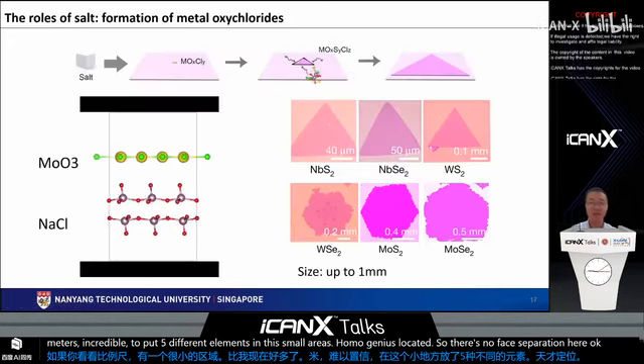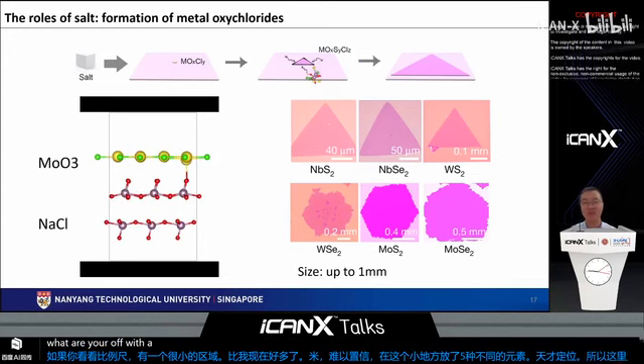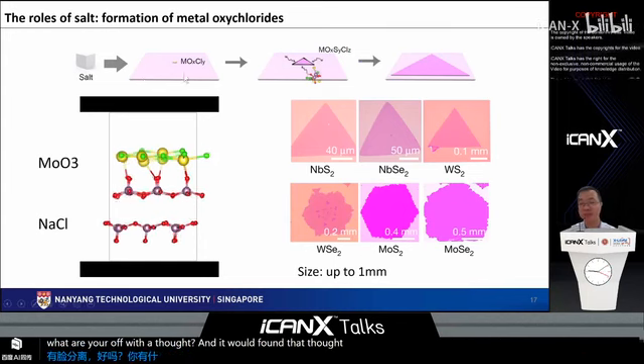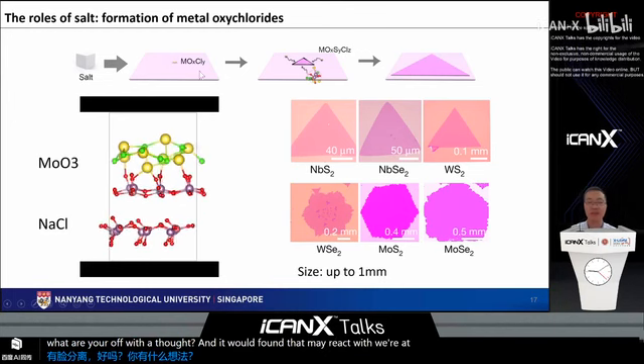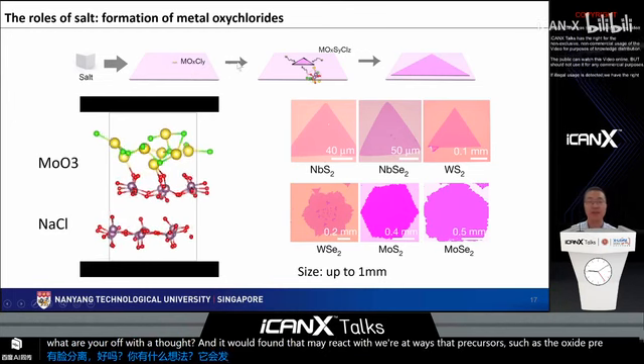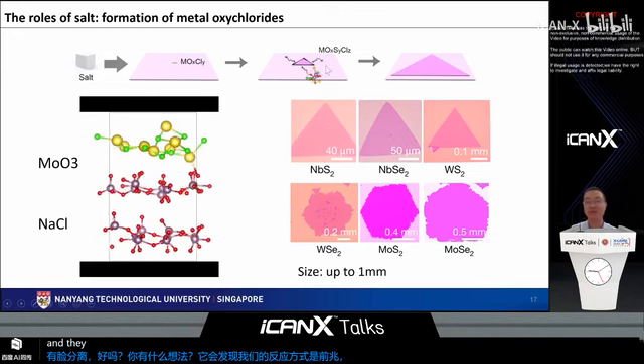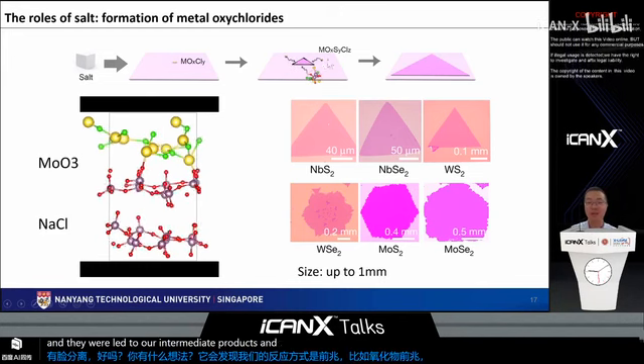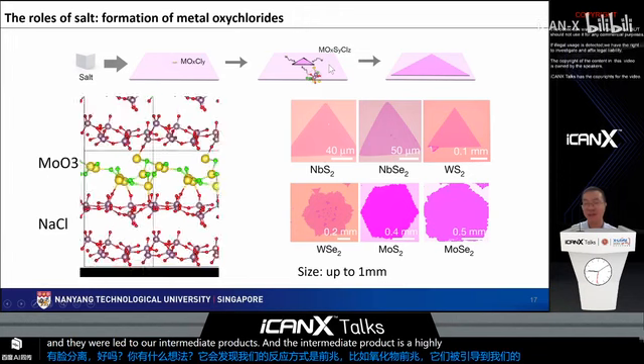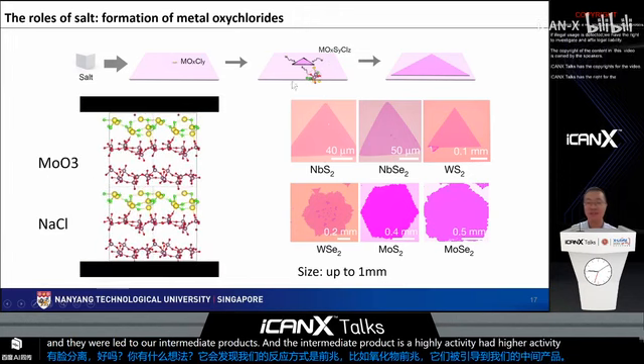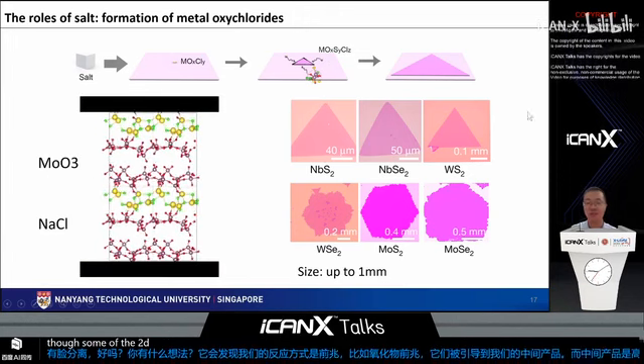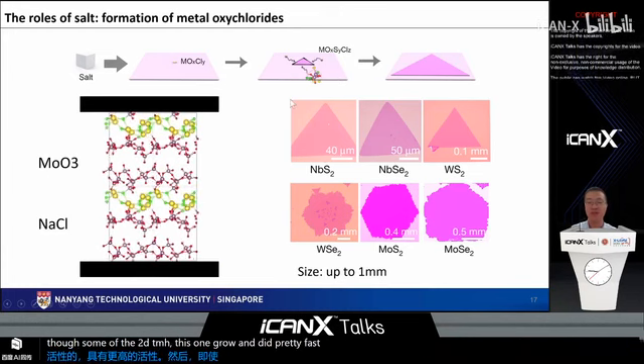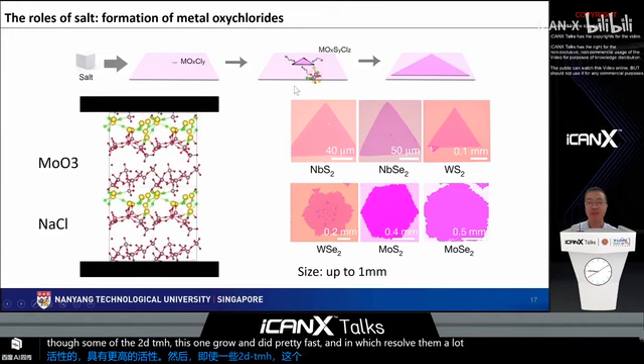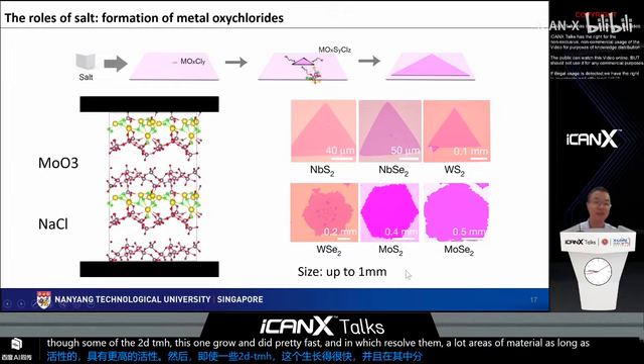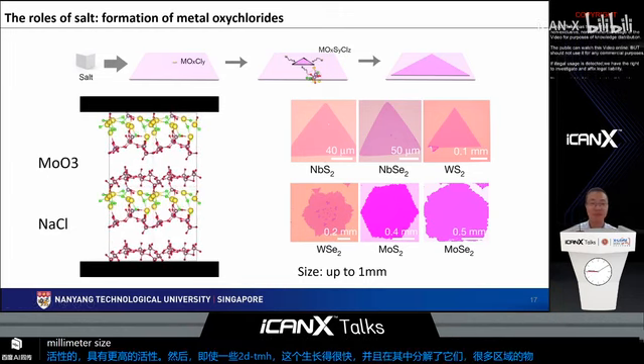Okay, and what's the role of the salt? We found that salts may react with the precursor, such as the oxide precursor, and lead to an intermediate product. This intermediate product has very high activity, so some of the 2D TMDs will grow pretty fast, resulting in a lot of areas of material as large as 1 millimeter in size. Okay, so this is the story about the growth part.